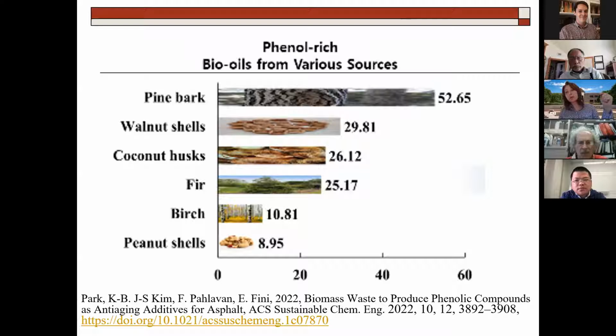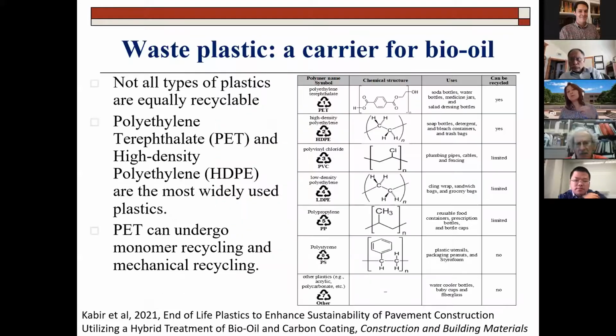And keep that in mind, these are biomass. So the CO2 from air went into this biomass sequester. Now I'm getting this oil from it. Phenol-rich bio-oils are very strong antioxidants. So if I can reduce the oxidation phenomena even on the top layer, if I can block it right there and protect the bottom layer, that could be a benefit. In this paper, we actually showed that addition of phenol-rich bio-oil reduced aging significantly. So it worked, and the mechanism is that the phenol donates hydrogen and as a result reduces the oxidation and agglomeration. But I'll show you what happens if we add some carrier to that.